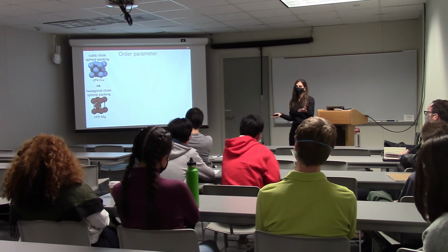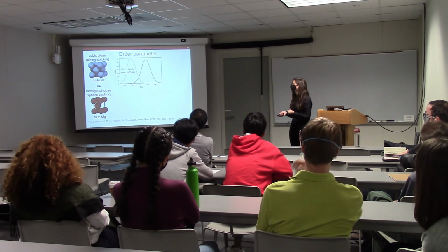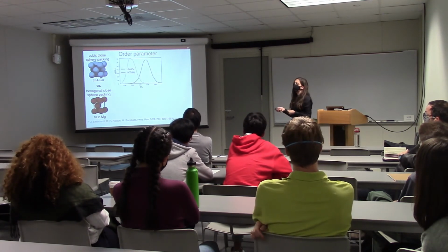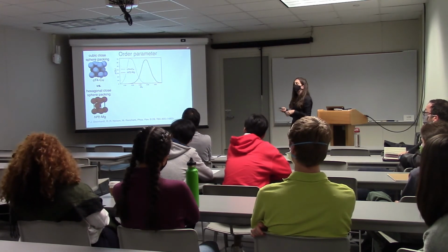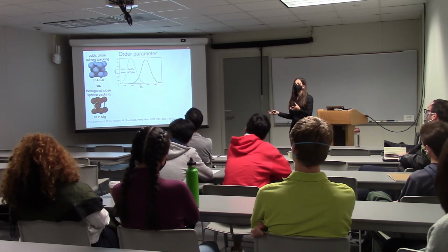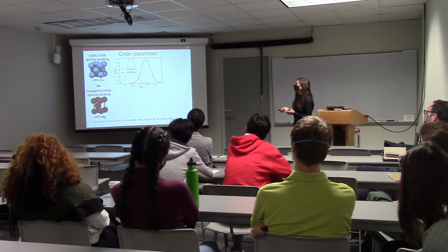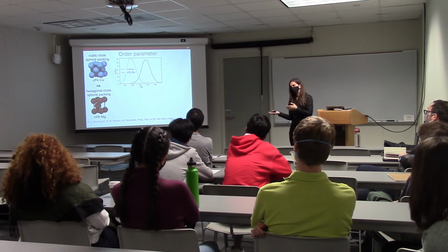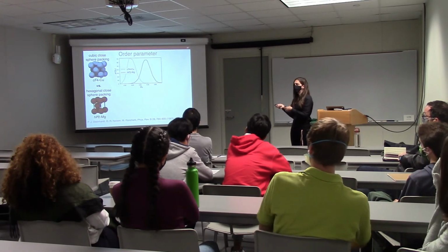So if you think about wanting to be able to distinguish solid from fluid like we did earlier, or in this case, the cubic from the hexagonal close-packed sphere, you can do that relatively easily with a low-dimensional order parameter that looks at the symmetries locally. It uses spherical harmonics to encode them, and you can tell them apart quite well. However, if you look at more and more complicated structures that are locally more and more similar, you'll not be able to tell them apart with something like this.